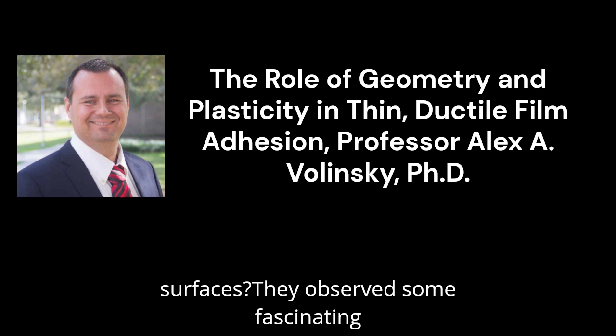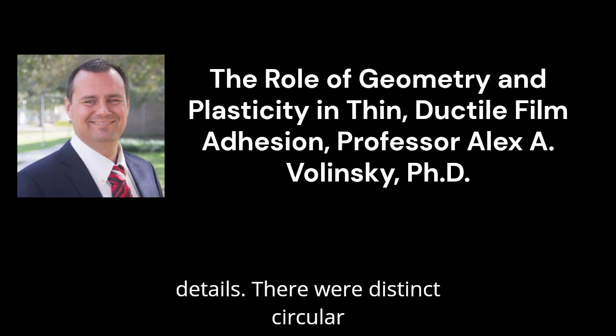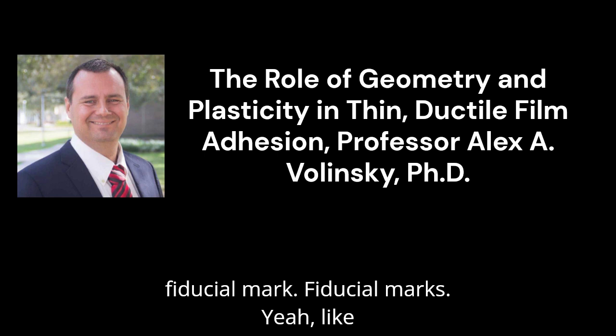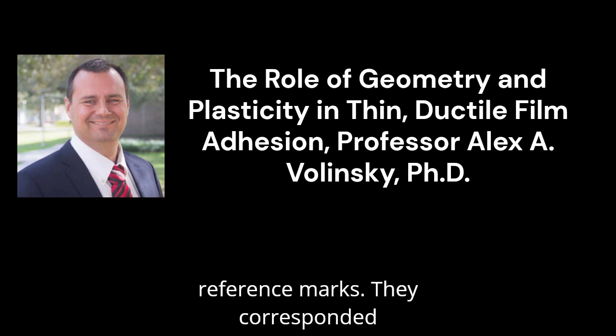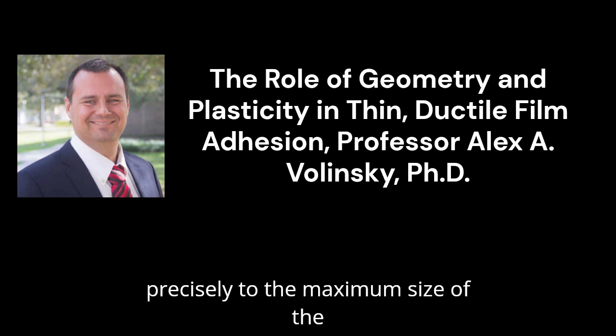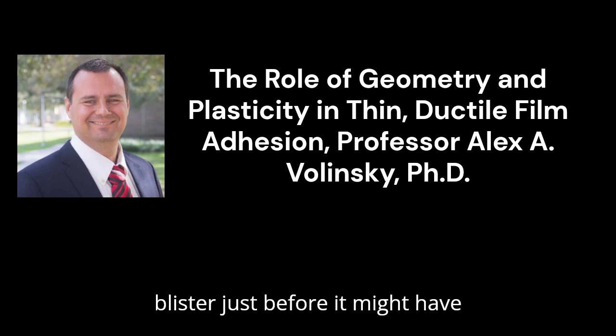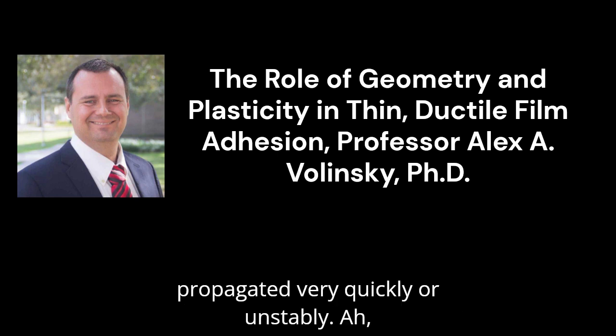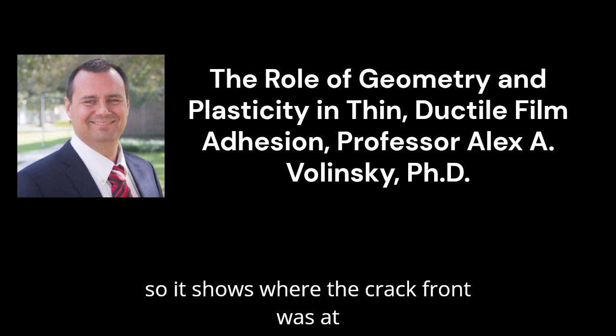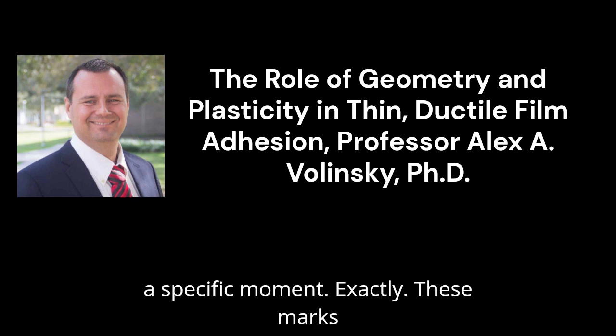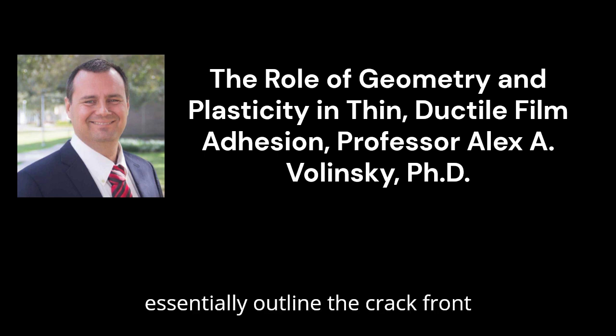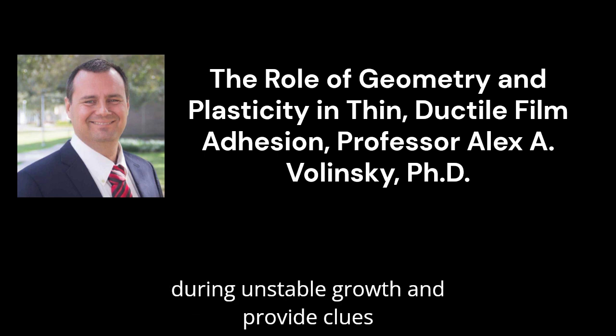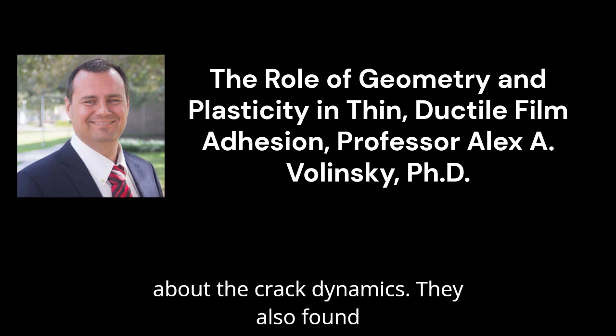They observed some fascinating details. There were distinct circular fiducial marks. Fiducial marks. Yeah, like reference marks. They corresponded precisely to the maximum size of the blister just before it might have propagated very quickly or unstably. Ah, so it shows where the crack front was at a specific moment. Exactly. These marks essentially outline the crack front during unstable growth and provide clues about the crack dynamics.